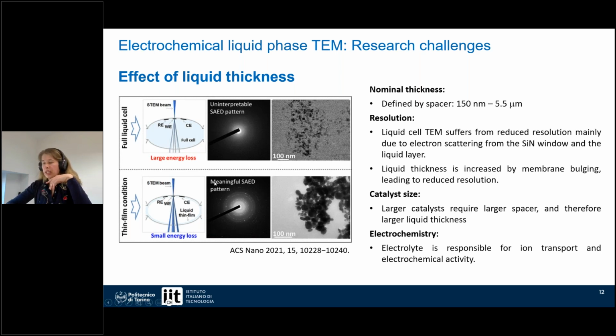It was shown in the literature that performing electrochemical water splitting in situ can generate a gas bubble. And with this, we can reduce the thickness of the liquid at the working electrode, so at the point where we want to perform our investigation.